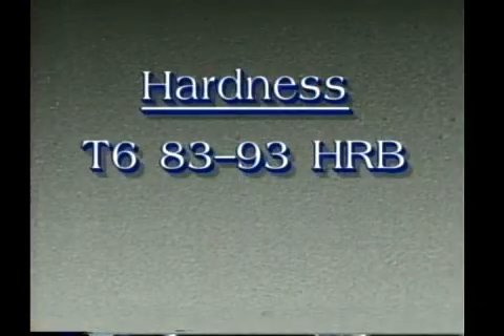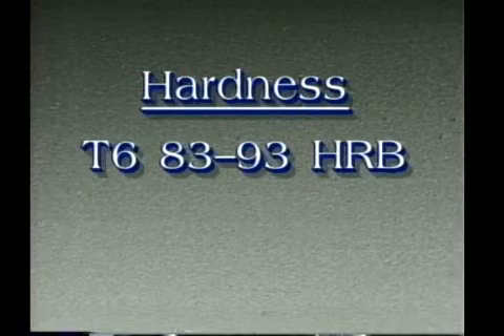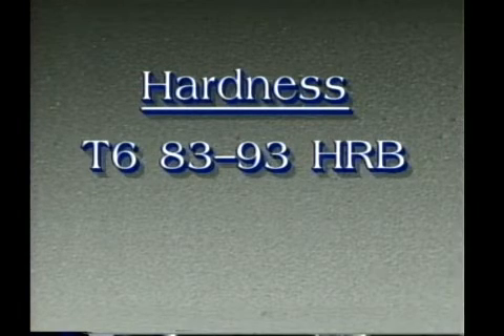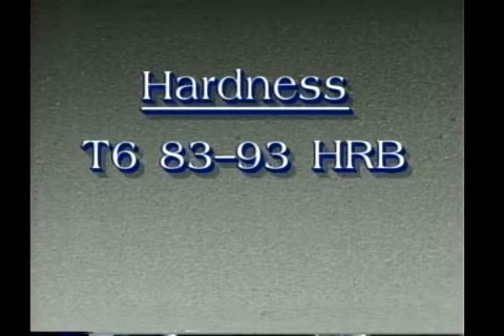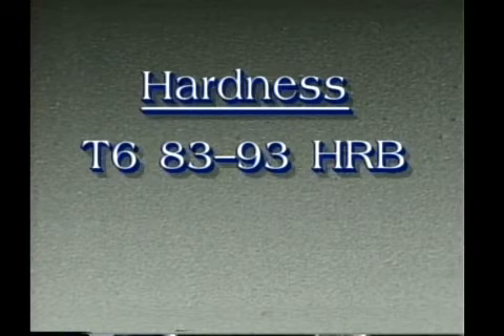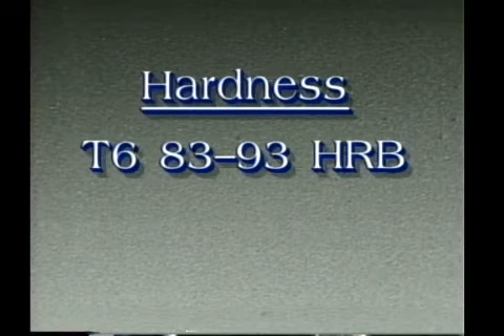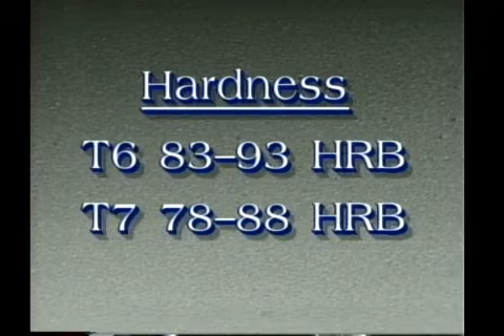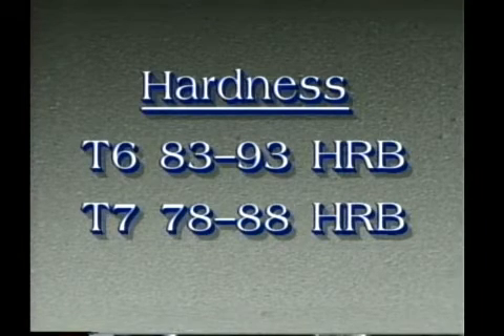Although the overaging did result in a reduction in hardness from the T6 condition, the T6 temper generally resulted in Rockwell B hardness readings from 83 to 93, while the T7 temper showed values of 78 to 88.